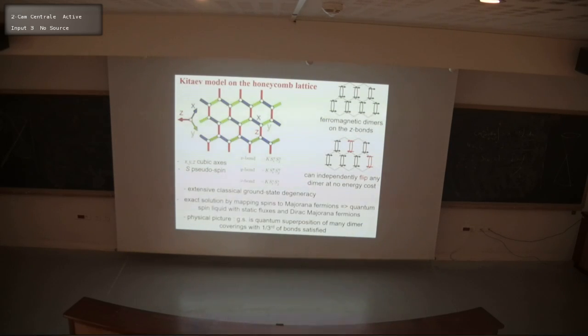So as Lucille introduced this morning, the Kitaev model on the honeycomb lattice is a model of Ising exchanges on every single bond, but with the particular feature that there are three families of Ising exchanges associated with the three different types of bond orientations, such that at every vertex there are bonds of three different colors, or three different preferred Ising directions, that meet at each point. And this incompatibility between the Ising directions is really the origin of quantum frustration and extensive degeneracy in the problem.